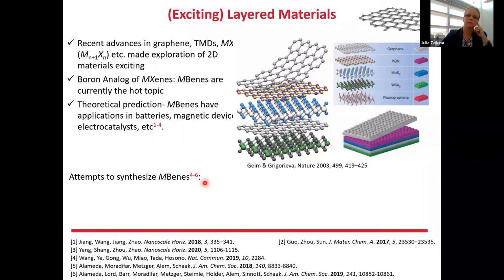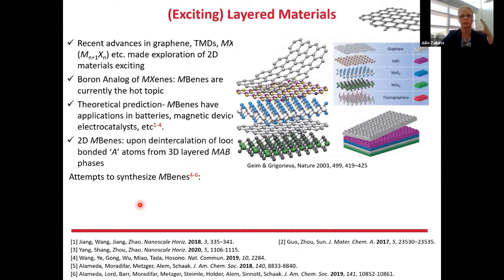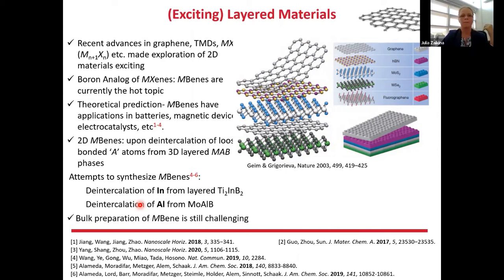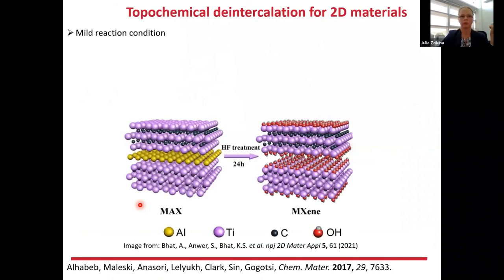And theoretical predictions suggest that those MBenes can find many applications in batteries, magnetic devices, and electrocatalysis. And so basically, we want to have a good layered precursor where we have a transition metal, boron, alternating with a layer of the secondary element, which would be easy to remove. Yeah, and even though it is all good on paper, there are still no reports on synthesizing those two-dimensional MBenes, two-dimensional borides. But one of the possible ways to make it is to use a similar approach which was previously used to synthesize two-dimensional carbide materials. So we can do this by using topochemical deintercalation.